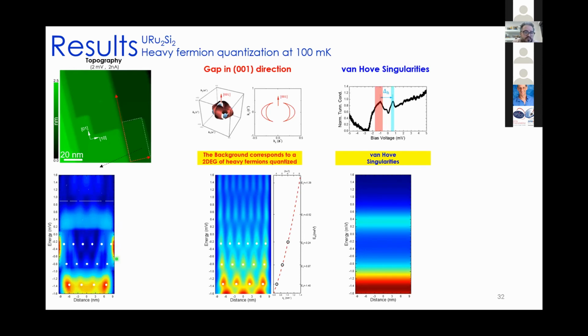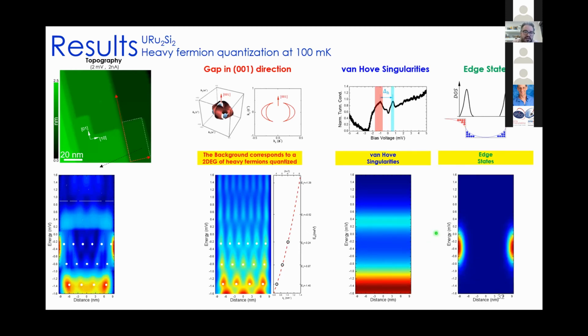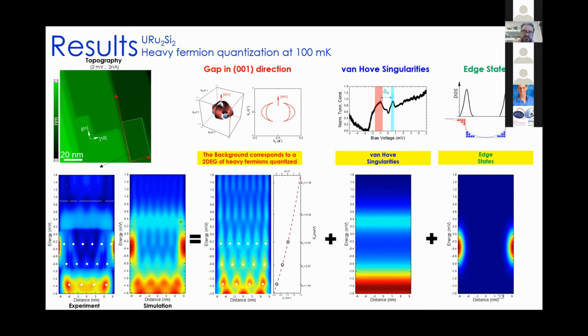And also, if we check a little bit in more detail the experimental result, we observe here also that we have an increase of the conductance just at the borders of the steps. And these two structures at the border are edge states. They appear here because we have a redistribution of the electronic charge just at the edge of the step, and I'm not going to enter into detail here either. So we simulate the edge states as two-dimensional Gaussian functions. And now we have all three ingredients, and if we put all these ingredients together, we have this kind of simulation. And as you can see here, it is in good agreement with the experimental results that we have obtained.